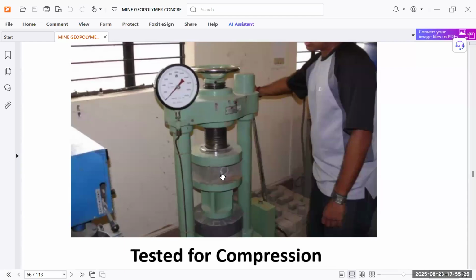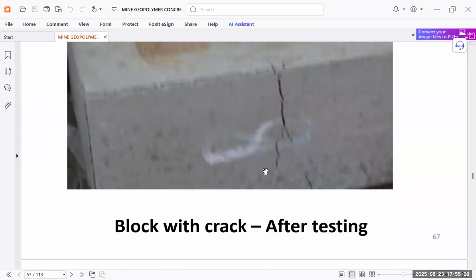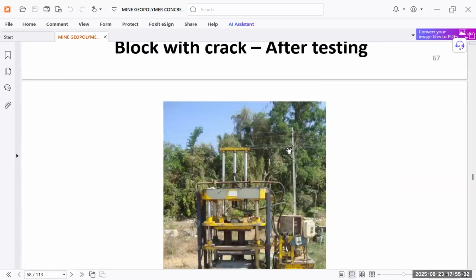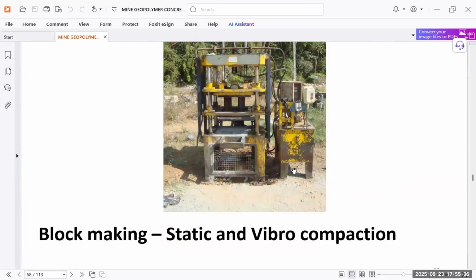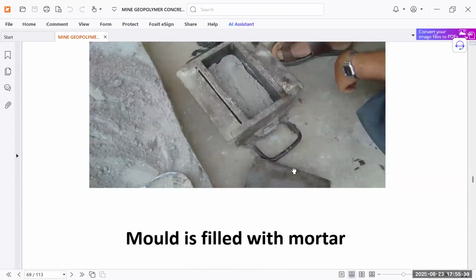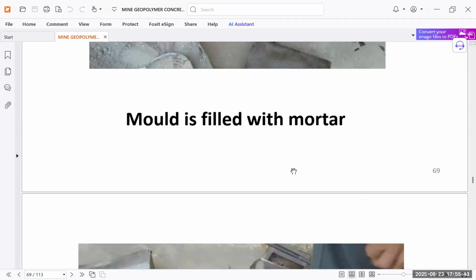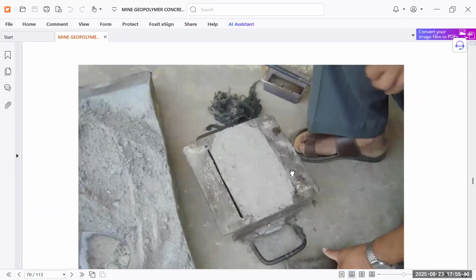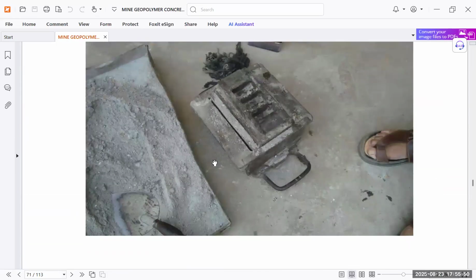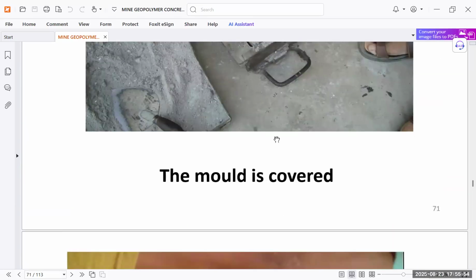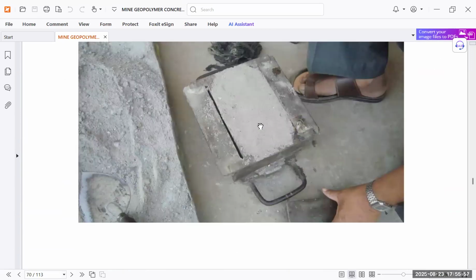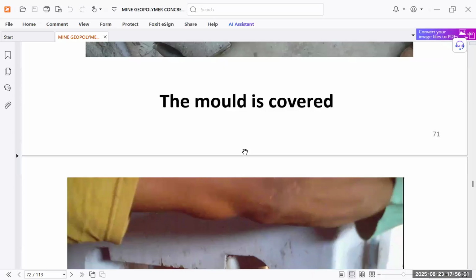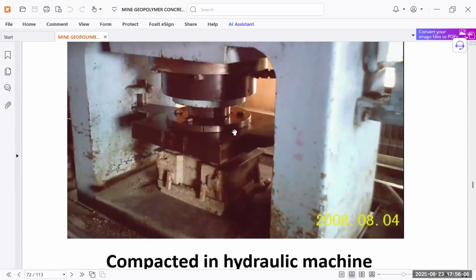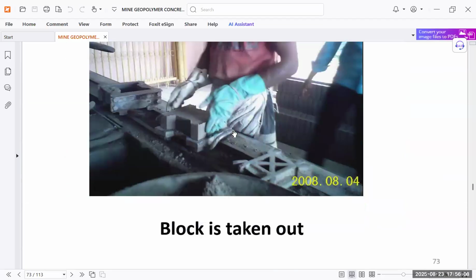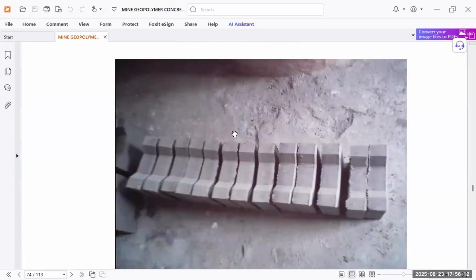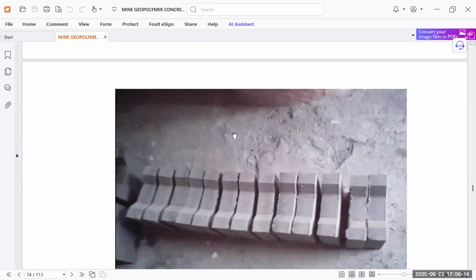Now the geopolymer block is tested for compression. A block with cracks after testing is seen like this. Then static and vibro compaction is there. It's filled with mortar. Again, it's filled with mortar. The cover is made like this. A compacting hydraulic machine will compact it, and then the block is taken out, and then cured in open air.